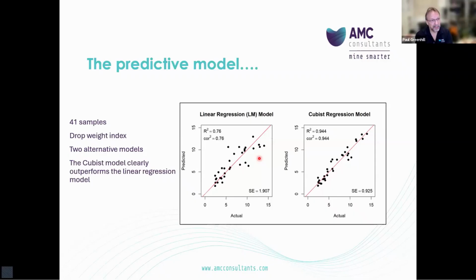So it's important to see here that within the two models, the cubist regression model has a reduced uncertainty when compared with the linear one. We can see the standard error for the linear regression model is about 1.9, and that for the cubist regression model is about 0.9. But how do we use this model to assess how many samples are needed? This data set, although not an unreasonable size in most of our experience, is really too small to demonstrate that the limit of metallurgical testing has been reached, or perhaps has not been reached.